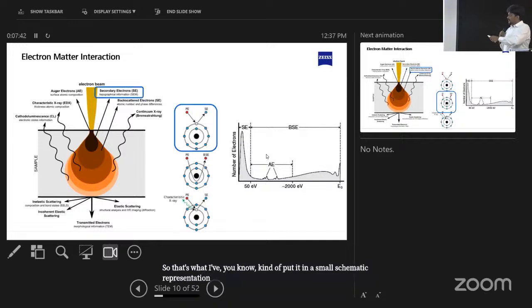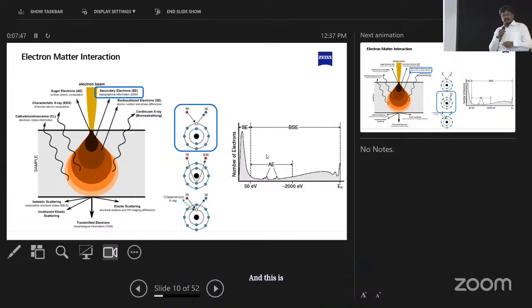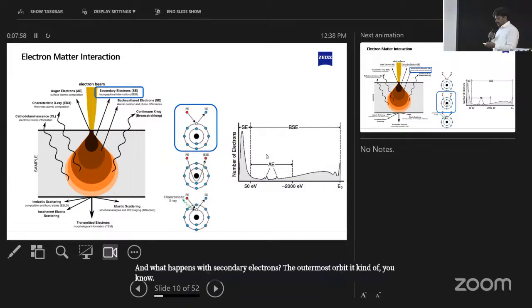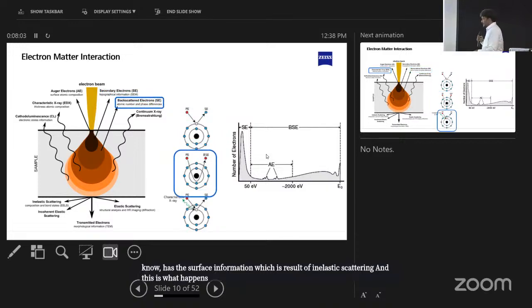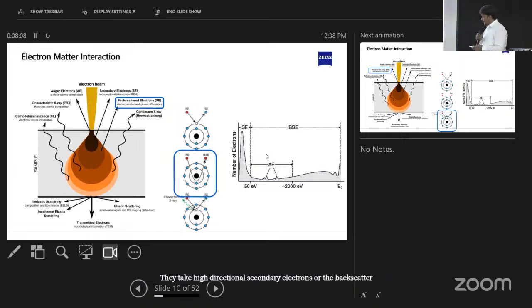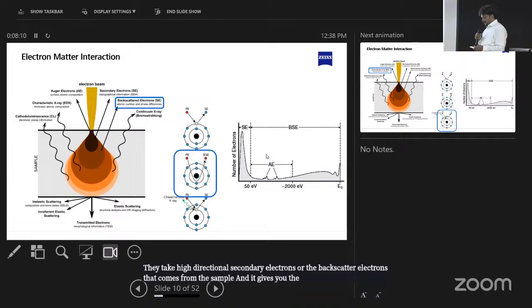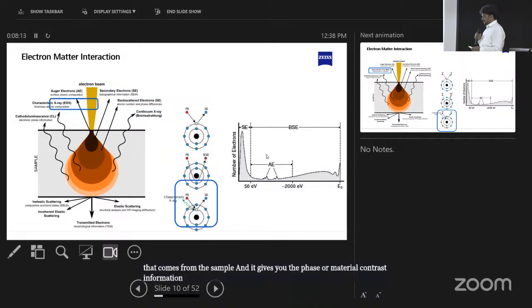So you can see here, this is the incident electron beam, and this is what we call the volume of interaction within the sample. What happens with secondary electrons, from the outermost orbit, is that they carry the surface information, which is the result of inelastic scattering. And this is what happens with elastic scattering: no interaction, but we get highly directional electrons, the backscattered electrons that come from the sample, and they give you the phase or material contrast information. And during the relaxation process, one form of energy gets emitted in the form of characteristic X-rays, which is used for your chemical composition analysis.